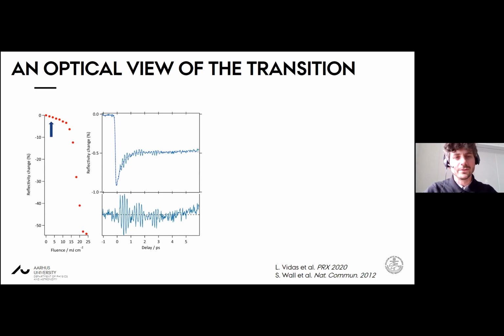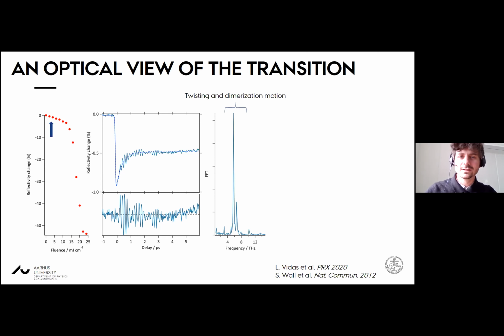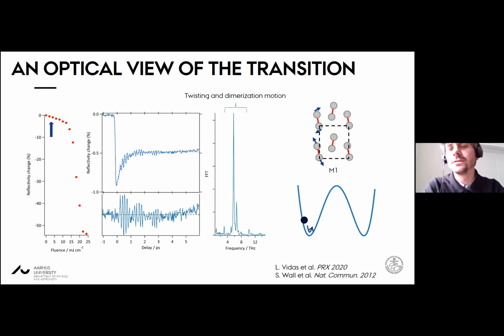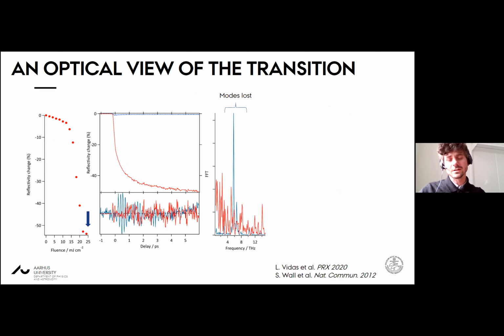If we look at what's going on in the low fluence regime, we see phonons, as many of you may be aware. These phonons oscillate, and there are actually quite a few phonons present in the system, but the main two occur at 5.7 and 6.7 terahertz, and these correspond to the bending and the twisting of the vanadium dimers. I've drawn them on the right here, separated from each other, but they're actually occurring on all the atoms within the unit cell in the same way. So there's a dimerization and the twisting. And as Stefan mentioned, these can be described by considering the system evolving on the free energy surface. And so this would again have to be a two-dimensional one, but the ball is rolling backwards and forwards inside this new potential.